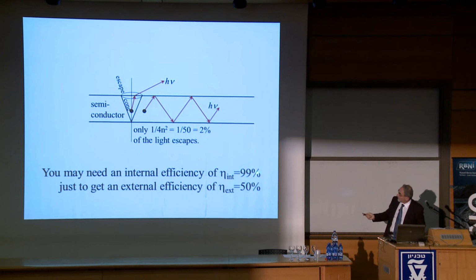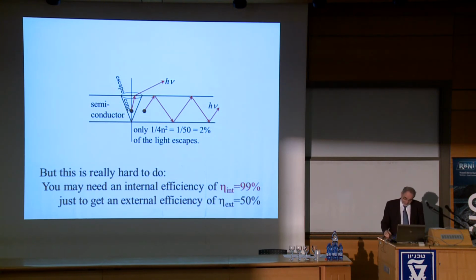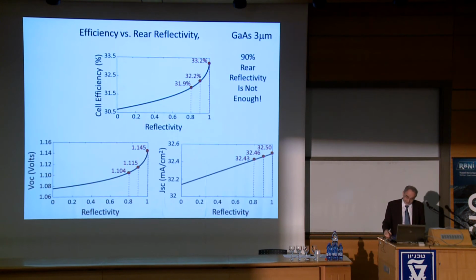If you hope to have, let's say, even only 50% external luminescence, then because the escape cone is so narrow, you need maybe 99% internal fluorescence yield. But this is very, very hard to do. 99% internal yield, you know, it's hard. It's achievable in gallium arsenide, but it's very, very hard to do.